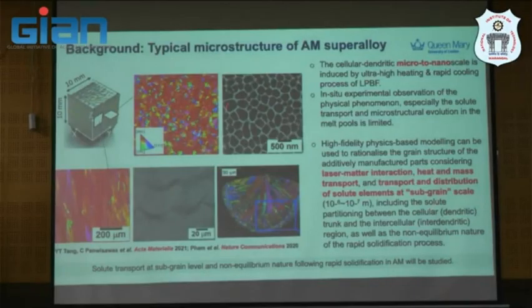So our inspiration to do the simulation in microstructure detail in nickel-based superalloy is, as you see in the build along the build direction and transverse direction, it clearly has different microstructure, from columnar grains to equiaxed grains, and this is with the cellular structure. Along the build direction, you may get this kind of melt pool and features at its time scale and its length scale. And the cellular dendritic structure here is in the micro to nano scale, induced by ultra high heating and cooling during LPBF.